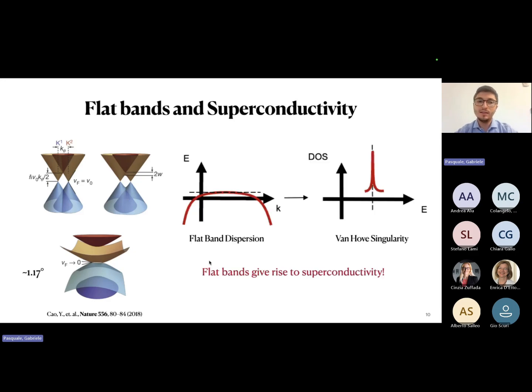We can think of it in the sense that if you have a flat band dispersion, at that energy that directly translates into a peak of density of states, which is called a Van Hove singularity. And Van Hove singularities combined with electron-electron interactions can give rise to instabilities and phase transitions such as superconductivity.